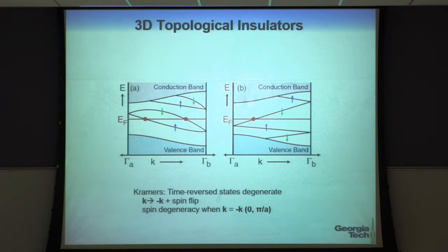Okay? So to do time reversal, I have to go to minus k, change the momentum, and basically flip the spin. What that means is that if I have a point like k equal to 0, where k is equal to minus k, then at that point, all I've got left is the spin flip, okay? That means that at that point in k-space, spin up and spin down have to be degenerate, okay? So Kramers degeneracy requires that. Also, for a periodic crystal at k equals pi over a in this one-dimensional case, out here also, because plus and minus pi over a, which I should have shown but didn't, are equivalent, they are degenerate. I also have to have spin up, spin down degenerate at that point also. Now, if I do it like this, so that I have an even number of crossings of the Fermi energy, then if I were to distort this thing, move these in energies, I could arrange to have the Fermi energy come at a place completely between the bands, and I could still have a gap.